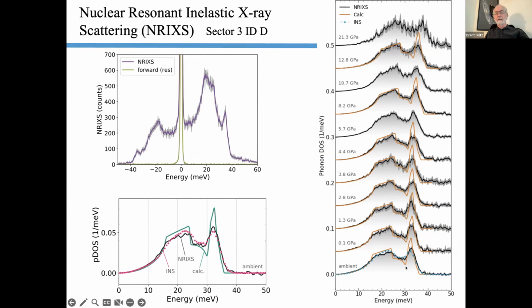Now you look at it as a function of pressure. There's a number of things to see. Generally it stiffens, although below the 4 gigapascals, the longitudinal mode peak at around 33 meV doesn't really change that much. It's mostly in the transverse modes.